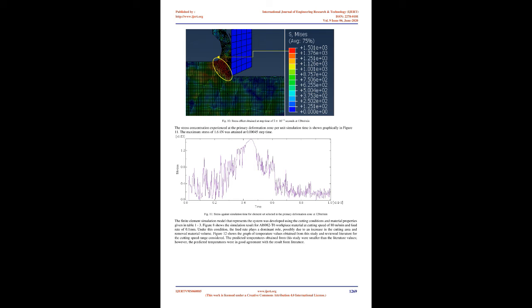1. Plane strain conditions were assumed as the cutting width was much larger than the undeformed chip thickness. 2. The tool edge is assumed to be perfectly sharp to keep the simulation as simplified as possible. The model was set up using the thermomechanical properties of the tool and workpiece, as illustrated in Table 1. The geometric model of the workpiece and tool was created as a 2D representation of orthogonal machining operation. The length and width of 2.5 mm and 1 mm respectively were used for the workpiece. It was partitioned at 0.2 mm from the top to represent the undeformed chip region. The tool was modeled as a rectangle with a height of 1 mm with a clearance angle of 7 degrees.